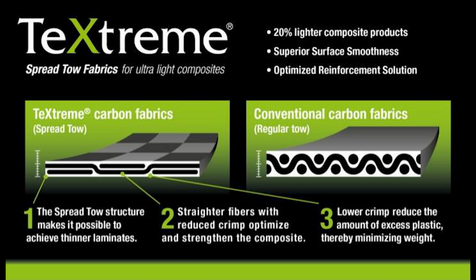So the properties of this weave are very close to a UD, but half of the fibers are going along the warp, and half of them are going perpendicular. Because the fabric is thinner, you can move the next UD layer underneath further out without making your laminate thicker and heavier.